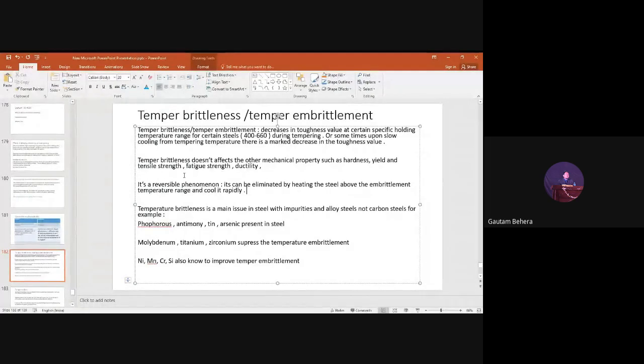The interesting point is this: temper brittleness doesn't affect the other mechanical properties. Even if the toughness is reduced, the strength will not vary, the hardness will not change, the fatigue strength will not change, the ductility will not change; only toughness gets reduced. And the important point is that molybdenum, titanium, and zirconium suppress temper embrittlement in steels. If you think your steel is going to show temper embrittlement during tempering, you can have these alloying elements. If molybdenum, titanium, zirconium are present, then it is okay. They suppress the temper embrittlement.